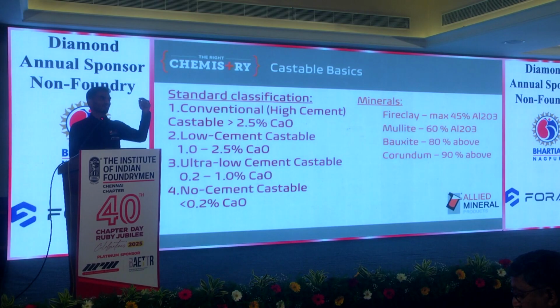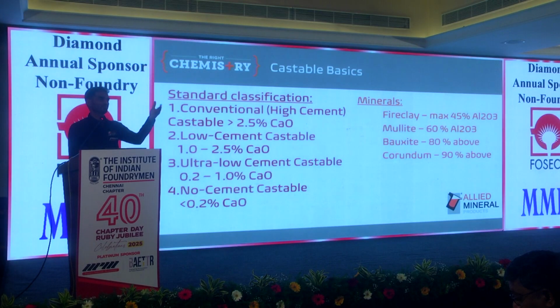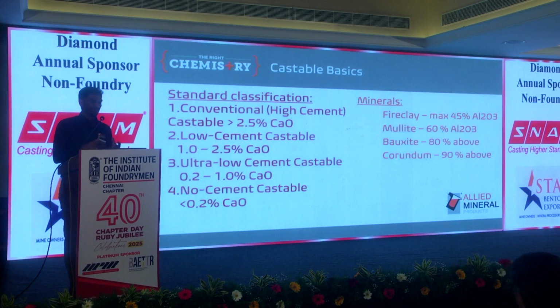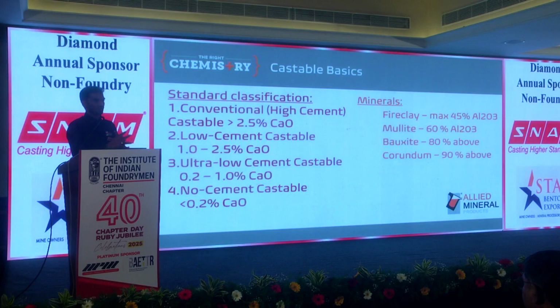In what way does this help? This was a question, when I talked about what we are adding to the castable, many people talked about binders. What are binders? Binders are cements. Now, there are advantages and disadvantages to each. When we add more cement, as in a conventional castable, you have more cement along with the refractory. When you heat it up, the cement will lose its properties over a period of time, and you will have a void structure which you can't visualize. But the liquid formation will vanish away faster. So conventional castable life will always be less compared to no cement castables.